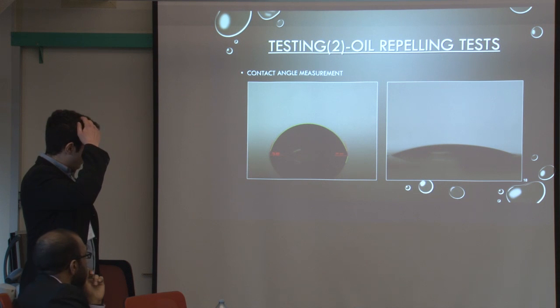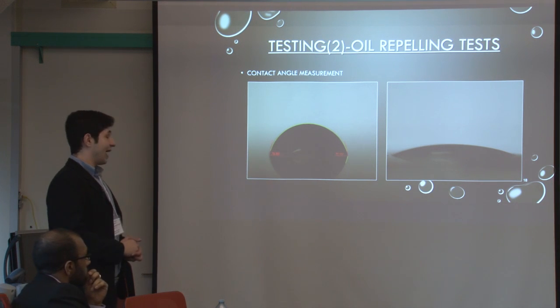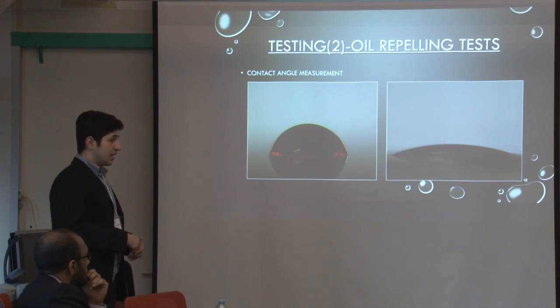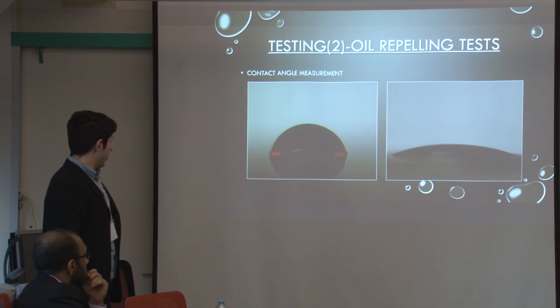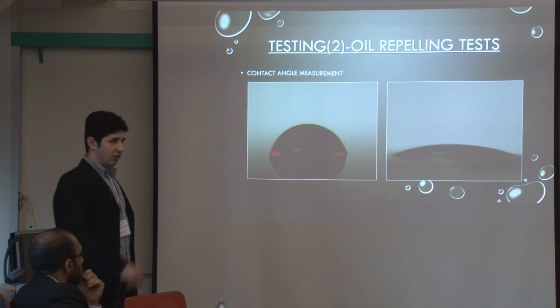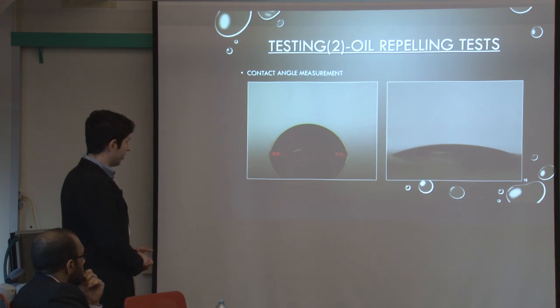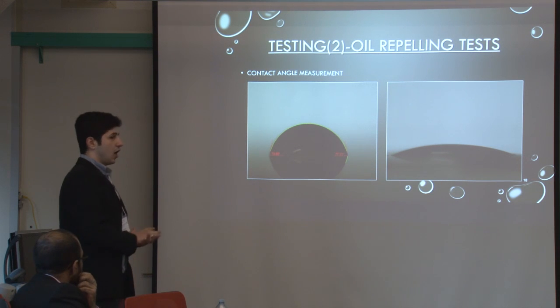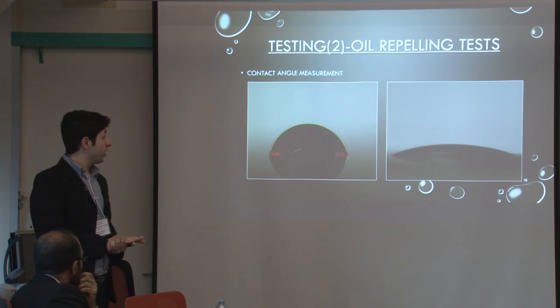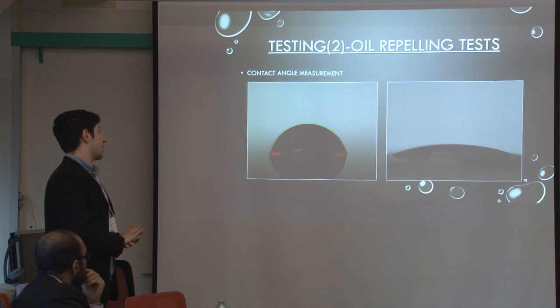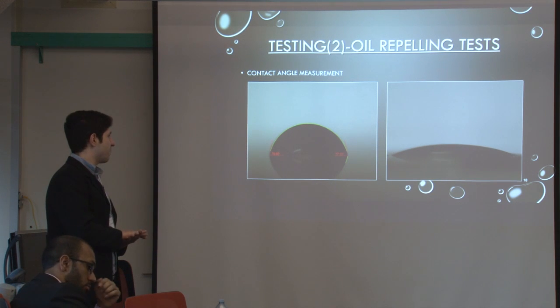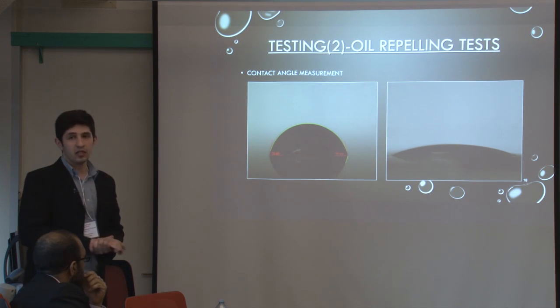We did the same test with oil. As you know, oil has a lower surface tension, so it's easier for it to flow on the surface. We were able to obtain up to an 80 degree contact angle with oil. The picture on the right shows an oil droplet on a plain glass substrate, where it gives us a very low contact angle, I think about 20 degrees.